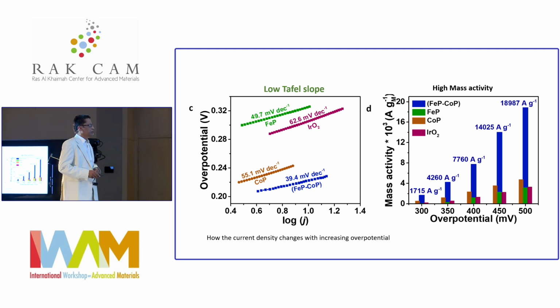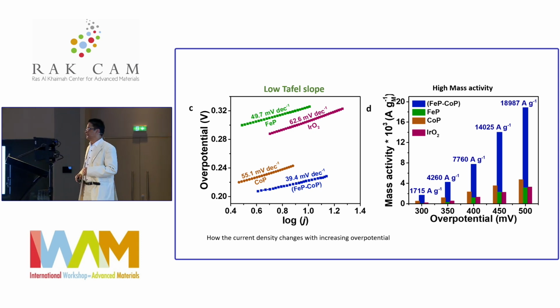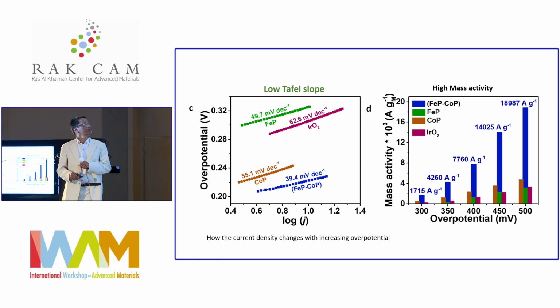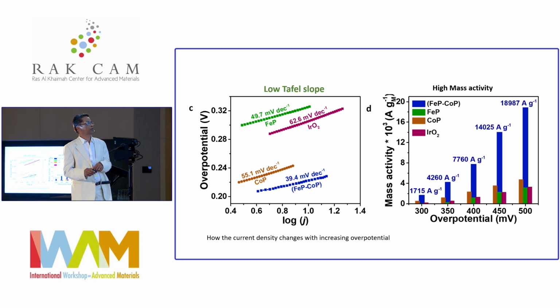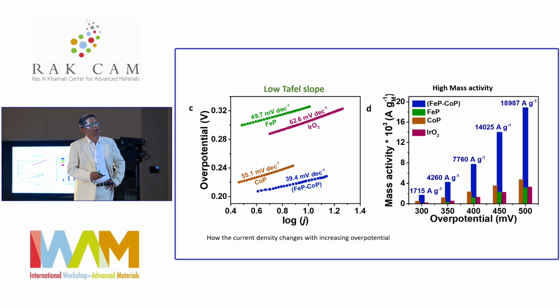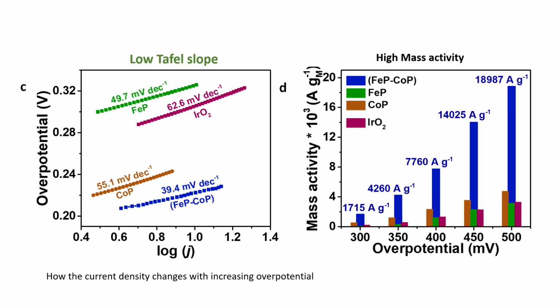And the Tafel slope, which is a measure of how the current density changes with increasing overpotential, shows a very good reduction, a low value for this FeP-CoP mixture. And the mass activity shows a huge increase. If you go to an overpotential of 500 millivolt, you will see almost 19,000 ampere per gram, converted to the weight scale of iron and cobalt. At lower overpotential, you will see nearly 1,700 ampere per gram. So it's a huge mass activity compared to cobalt phosphide or iron phosphide at any overpotential.